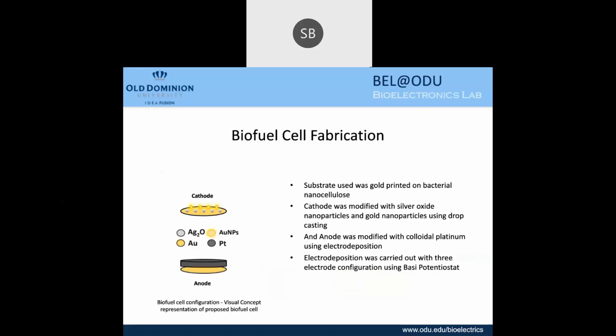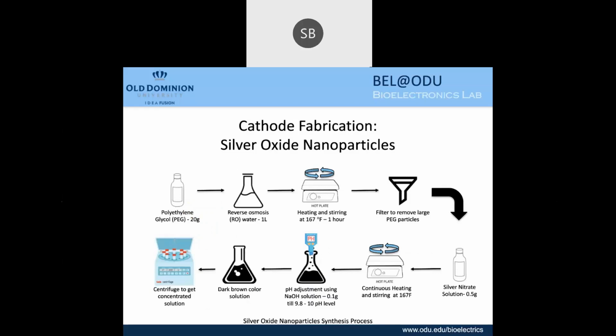For our proposed biofuel cell configuration, we used a substrate of gold conductive printed electrode on bacterial nanocellulose. As shown in the diagram, the cathode is modified with silver oxide and gold nanoparticles. For the anode, a colloidal platinum electrode was designed using electrodeposition.